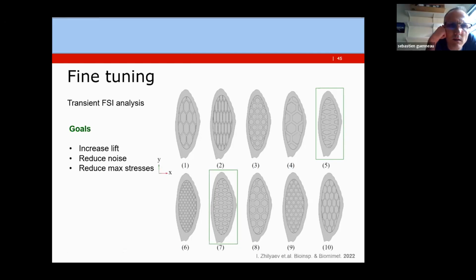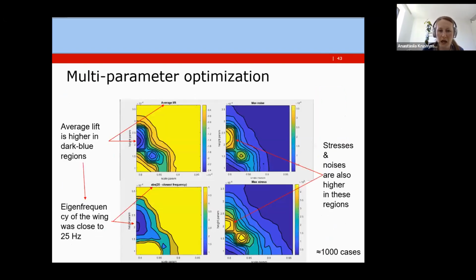Yeah. And it appears that some parameters are less relevant, so we can ignore them. And we do it not by running the optimization study in the classic sense, where we say that we want to optimize lift, but we do it by constructing these maps, which show us the influence of the interdependencies between the parameters. So here you can see, for example, that when the scale parameter along one of the axes is larger than 0.9, there is no effect. There is no dependence basically between this parameter and the parameter of the thickness of that element. So that means that the optimal designs are located in this region. And then we try to use these maps to find some optimized designs in terms of our targets. Yeah.